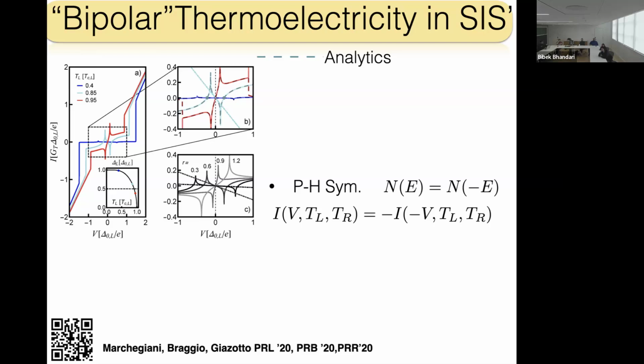And this corresponds to this point, okay? But you see there are 2 points. So it means that you have a system with a gradient of temperature, and you can have 2 different, opposite voltages. And this is something that I was stuck on. Honestly, I'm a theorist. I worked a little bit in thermoelectricity, and this struck my mind because it is something that you are not expected to see. In a certain sense, it's strange. Typically, systems are P-like or N-like, and they show different behavior. But this can be both P and N.